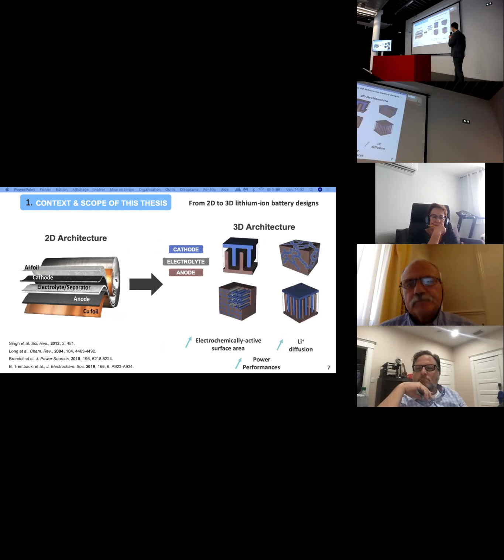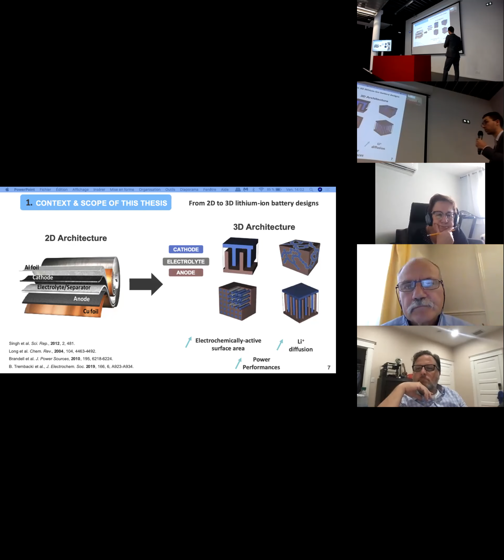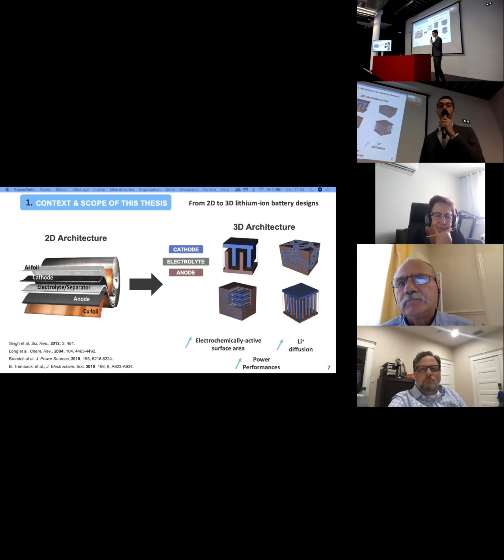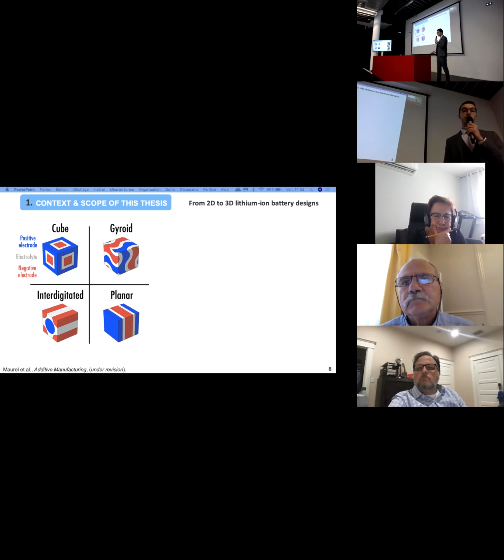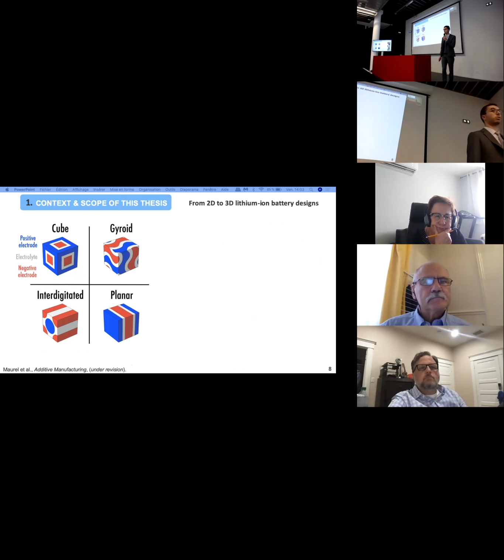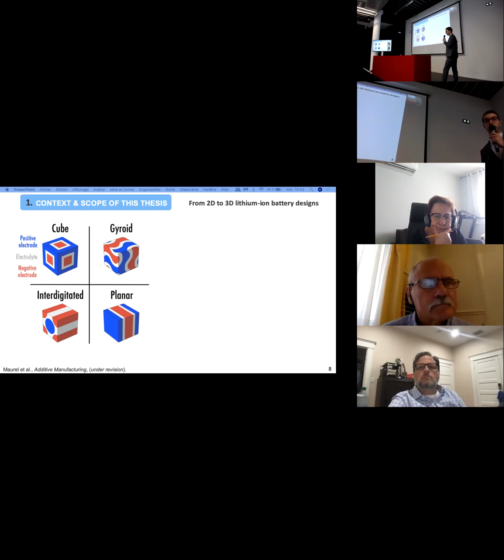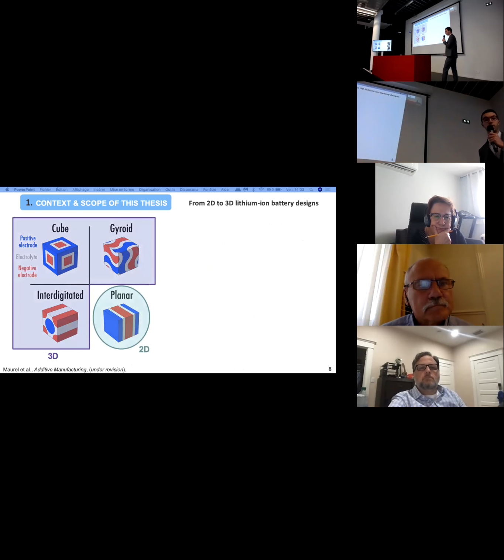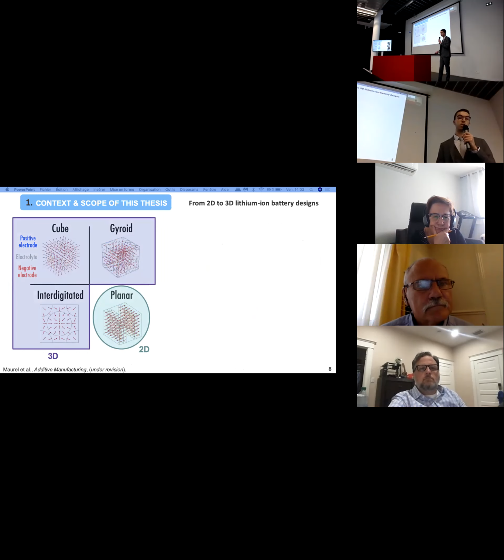And here, as you can see, it's due to the increased electrochemically active surface area. Also, the lithium-ion diffusion is greatly improved thanks to this kind of architecture. So actually, this trend here was confirmed during this PhD thesis. We did a modeling study here, and we compared some two-dimensional architectures of the battery with three-dimensional architectures. And so based on the results that I'm going to show here today, first of all, we saw that here